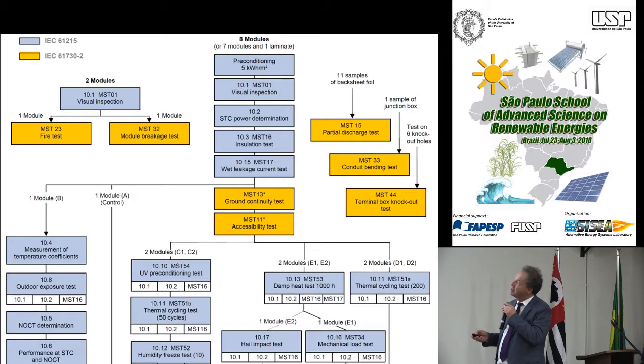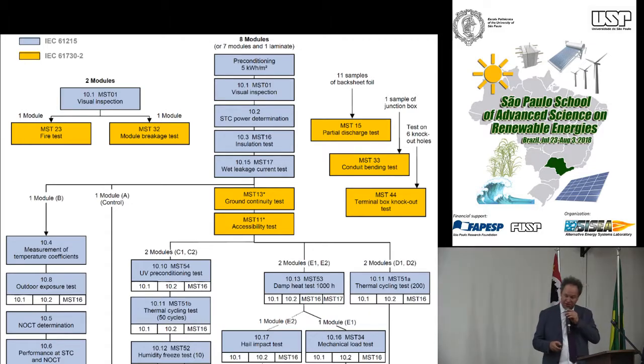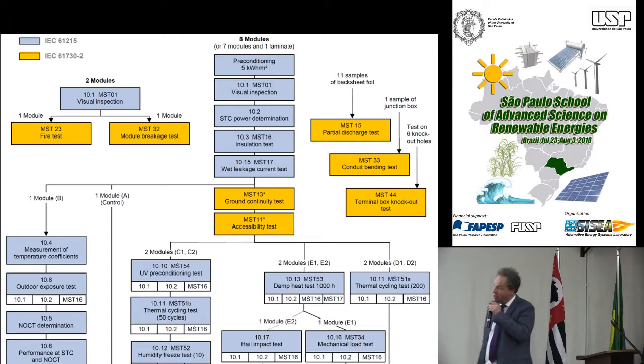Then you repeat the test: visual inspection, you repeat power determination, and so on, and the leakage test. So you see whether the module after these tests is performing worse than it did before. Same as the thermal cycling test. That means thermal cycling between minus 40 degrees and plus 80 degrees, and repeat it 50 times. And then you see whether the module suffered by that, by repeating insulation test and the visual inspection and measuring the power output.